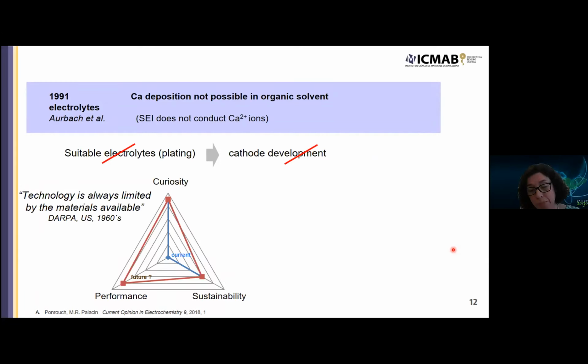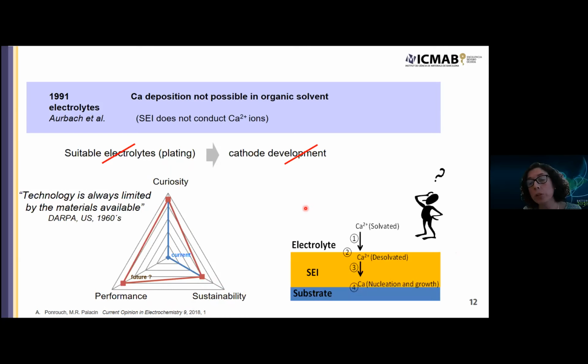So I like to use this graph, which is imported from Patrick Johansson, who likes to show these ideas about why we do something. And in this case, we were interested in the potential performance of these calcium batteries, because this technology could be sustainable, especially if for the cathode we would use abundant metals, but also we were sparked by scientific curiosity. So the first question was to know why the electrodeposition of calcium is not feasible. Is it because the migration of solvated calcium ions in the electrolyte is hindered, or the desolvation of calcium ions at the surface of the SEI, or transport through the SEI, as was thought before, or even nucleation?